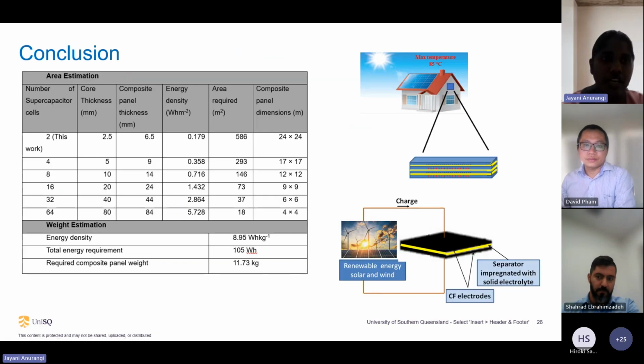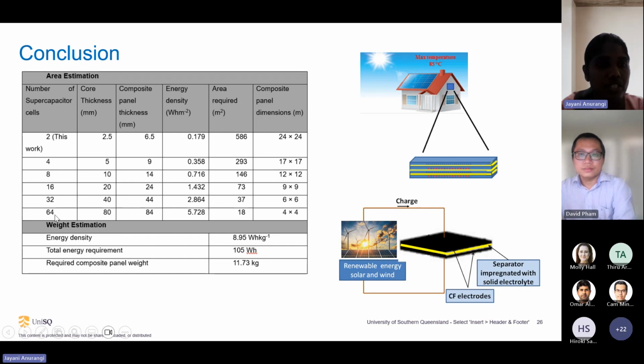Therefore, as the conclusion, I calculate if I increase the number of cells in the core layer up to 64, because my developed sandwich composite has 2 cells. If I increase it to 64 cells, the total panel thickness increases to 84 millimeters, but the size is reduced to 4x4 dimensions. So that is actually an acceptable size. Using this panel, I can light up a typical room for 5 hours with 3 LED bulbs of 7 watts. After that, I calculate the weight of the panel. According to the density, my total panel weight will be around 11.73. Actually, that is the conclusion of this project. So using this much weight, I can light up a typical room for 5 hours.